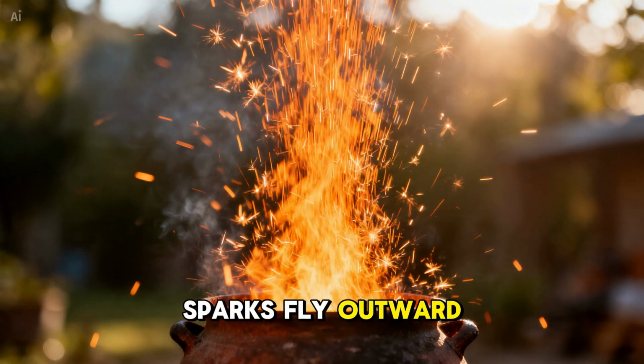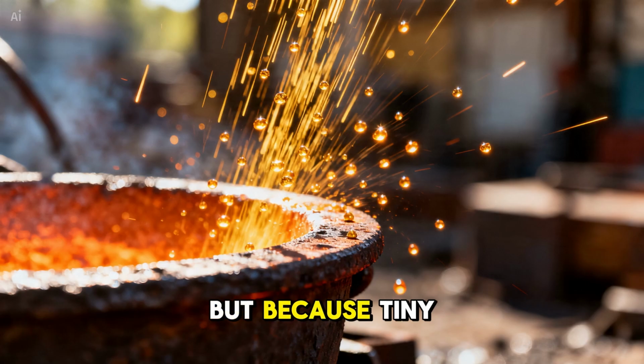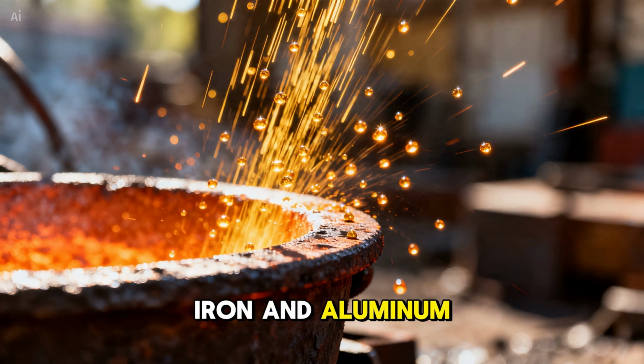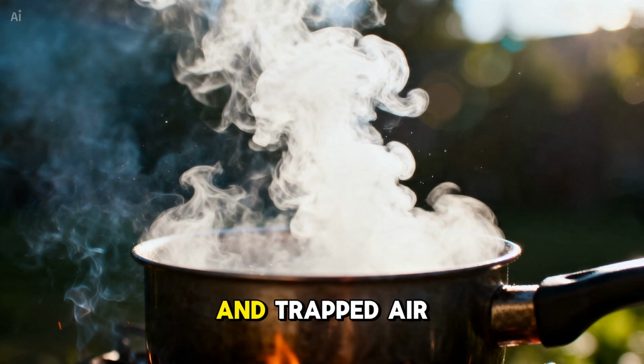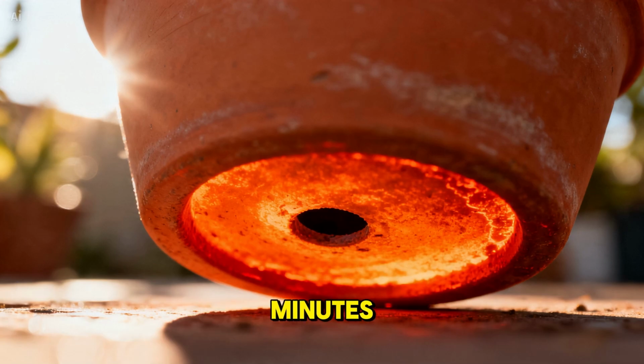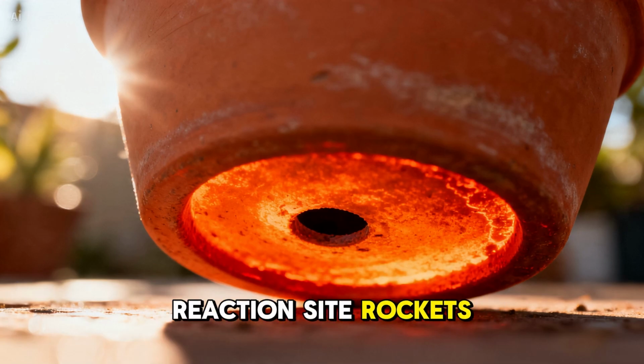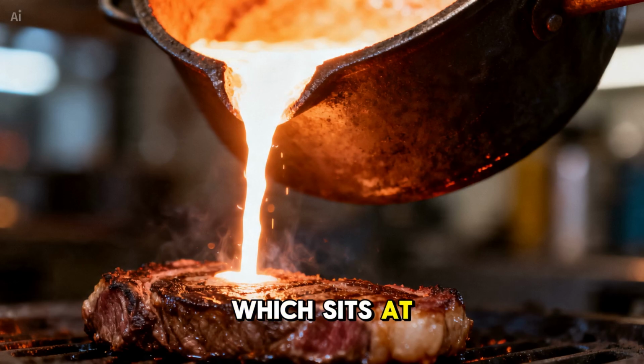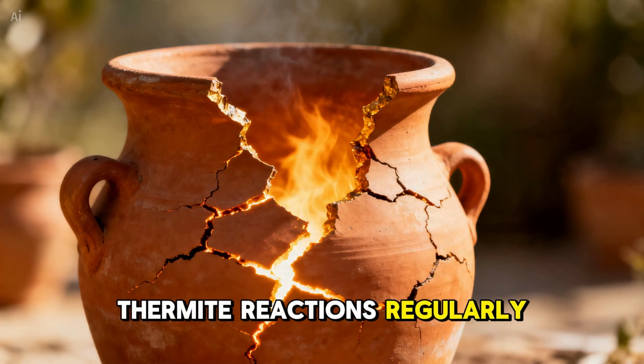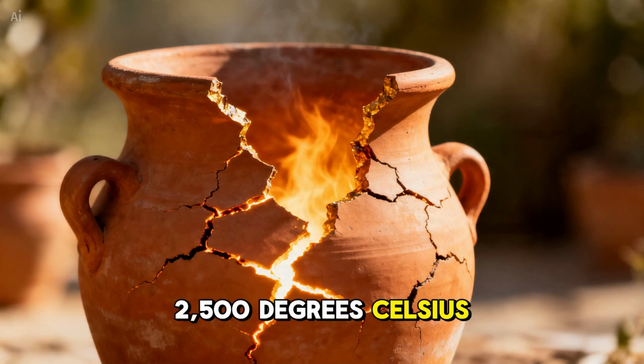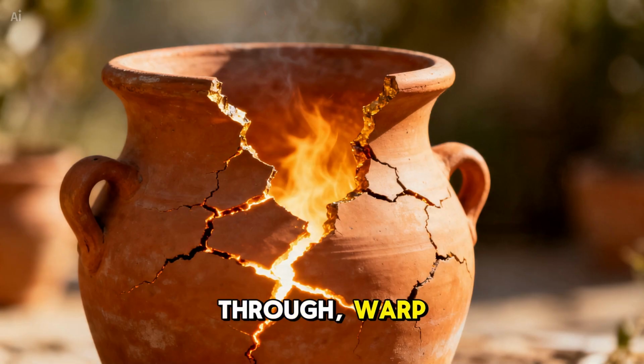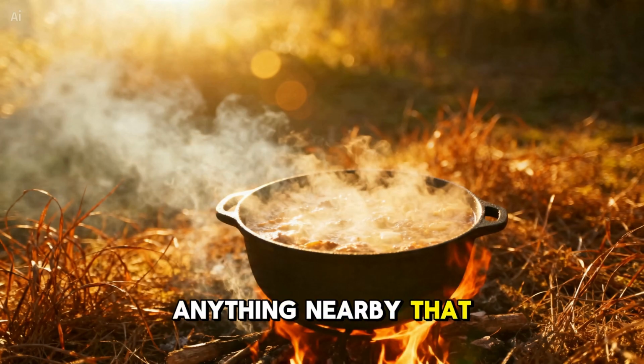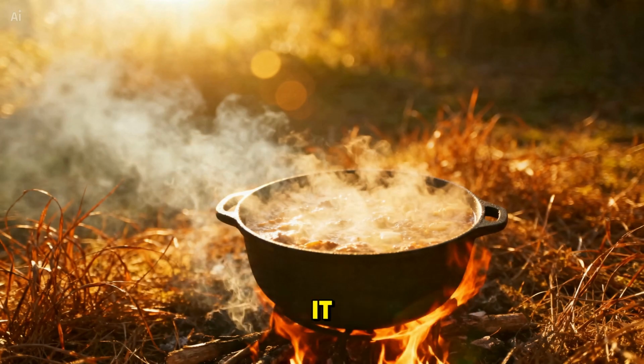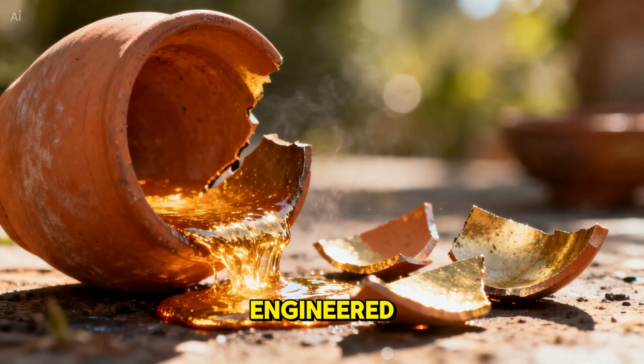Sparks fly outward, not because the reaction is unstable, but because tiny droplets of molten iron and aluminum oxide are being ejected as gases, and trapped air pockets are heated instantly and expand. Within seconds, not minutes, seconds, the temperature at the reaction site rockets past the melting point of iron, which sits at roughly 1,538 degrees Celsius. Thermite reactions regularly exceed 2,500 degrees Celsius, which is hot enough to melt through, warp, or ignite almost anything nearby that isn't specifically engineered to survive it. And a terracotta flower pot was not engineered to survive it.